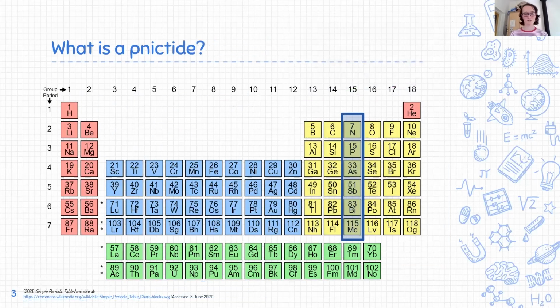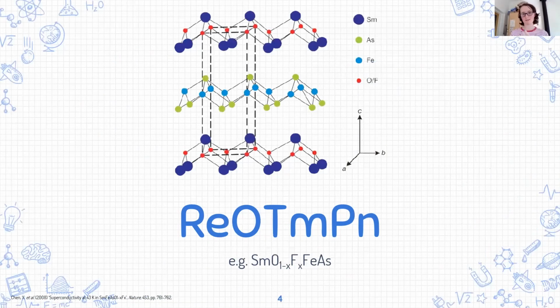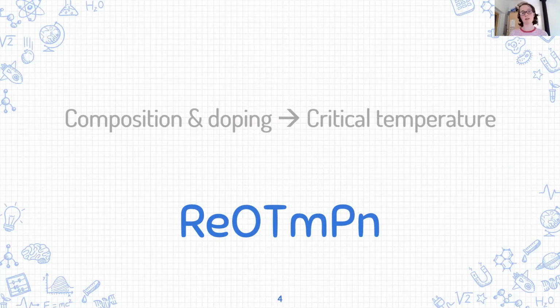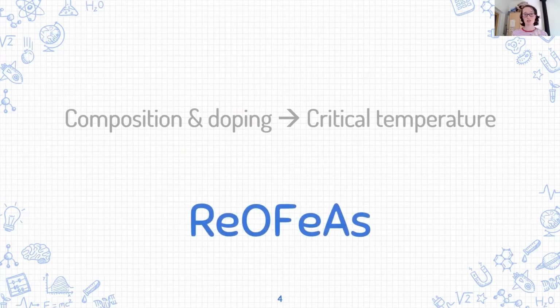So next question, what is a pnictide? The pnictogens are just the elements in the nitrogen group of the periodic table. So pnictide superconductors are a family of superconductors, all of which contain at least one of these elements, normally bonded to a transition metal. And the ones I was looking at were the 1111 structure type, which look like this. They all consist of a layer of a rare earth element tetrahedrally coordinated to oxygen and a pnictogen tetrahedrally coordinated to a transition metal. And I was investigating how their composition and their doping changes their critical temperature. Now, for the sake of this presentation, I'm going to be specifically talking about those where the transition metal is iron and the pnictogen is arsenic.